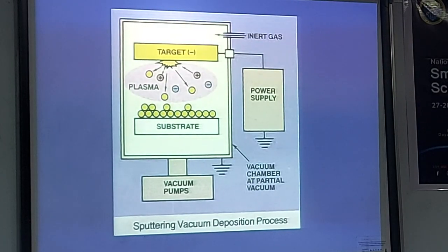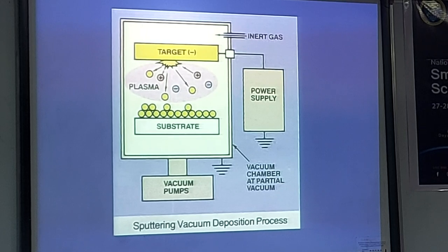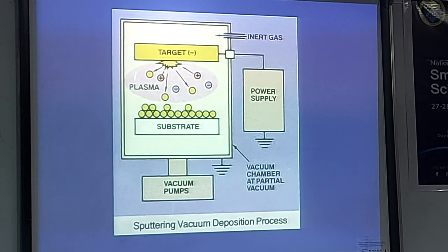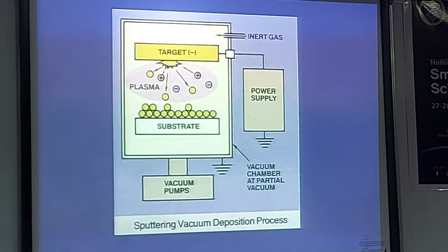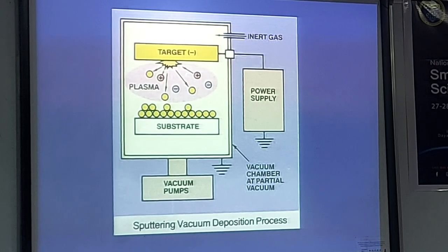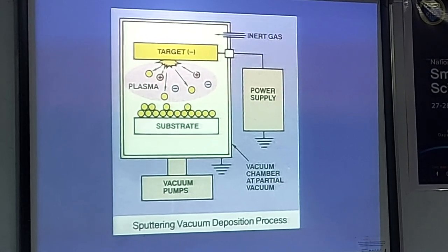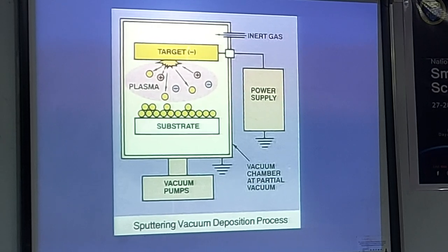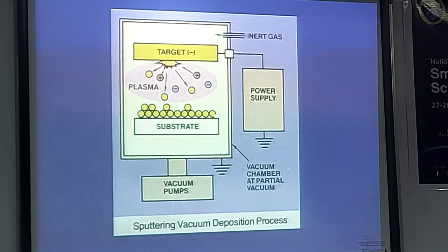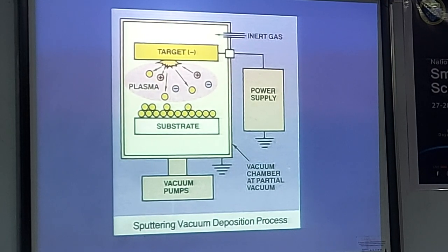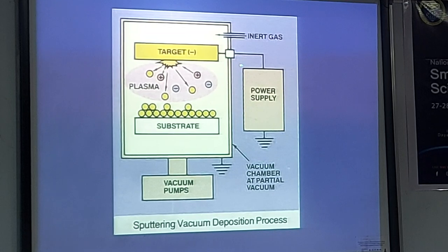So this is how the process of sputtering takes place. We have a target which is at a negative potential, and a substrate which is at a ground potential. Whenever the ions go and hit the target, material gets removed and settles down on the substrate. This is an atom condensation process. Depending on the potential applied and the various sputtering process parameters, we can tell the properties of the film deposited on the substrate. So if you use a direct current with two electrodes, it is called DC sputtering. There are various modifications of this.